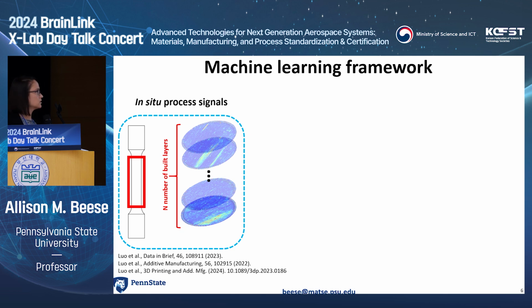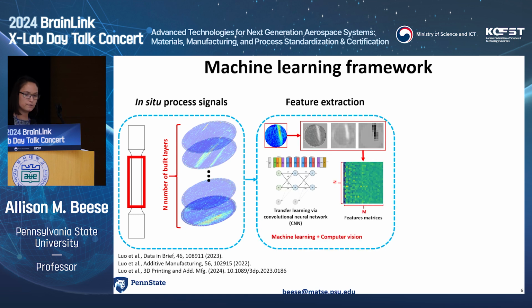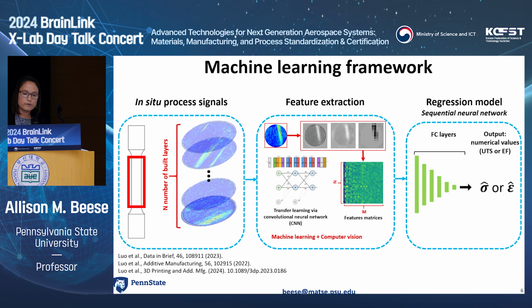And so we moved to a machine learning and computer vision type framework where we say, okay, let's take a look at the data that we have from each of those samples and each of the layers. And we put those into images as shown here. And we want to pull out the information and try to see if we can find something that tells us whether our properties are good or bad. So we use feature extraction. We use transfer learning to pull out the features and compress the data from these signals. And again, we have 500 layers of data for each sample. And then we use the compressed data along with our known values for strength and ductility on a subset of our samples to train a regression model.